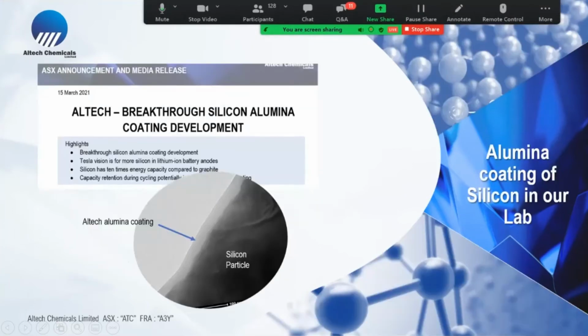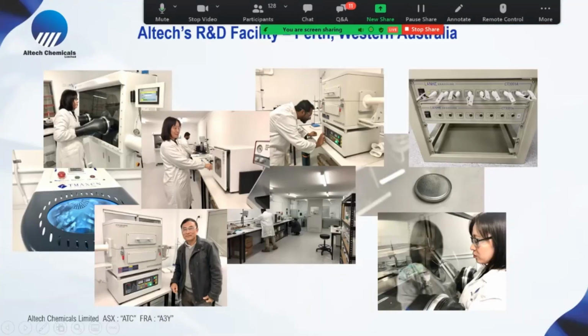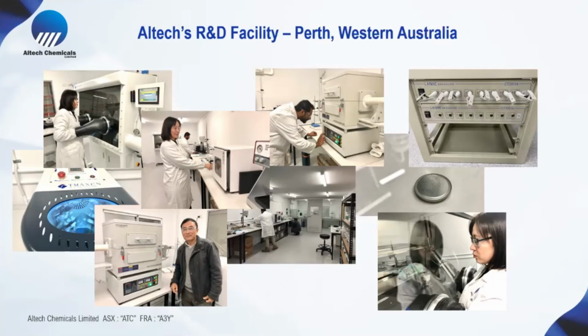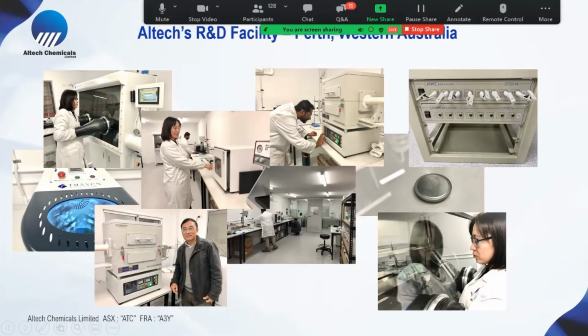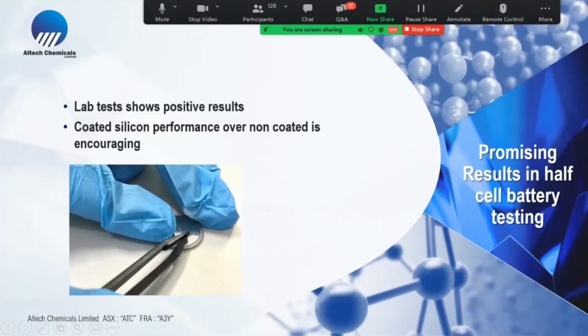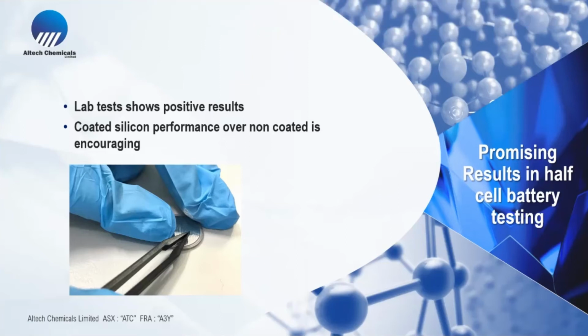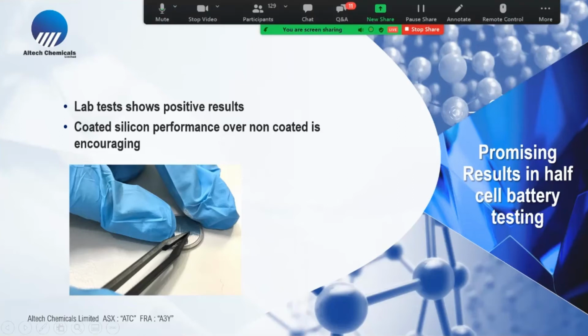Well, essentially, we've done our laboratory tests. We've managed to coat silicon particles with a very thin layer of alumina. And we believe that our alumina can contain the fracture of the silicon and also reduce that first cycle loss. All our technology is developed within Australia in our laboratories in Perth. And we have so far shown very positive results with coated silicon performance over non-coated silicon performance. And there is still further work to be done, but very encouraging results so far.